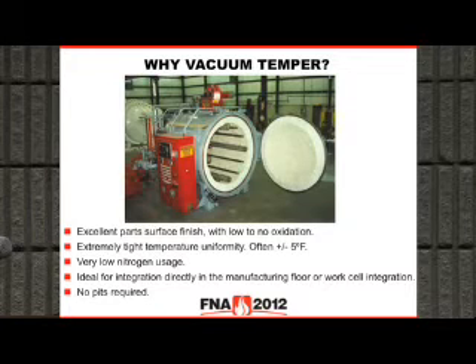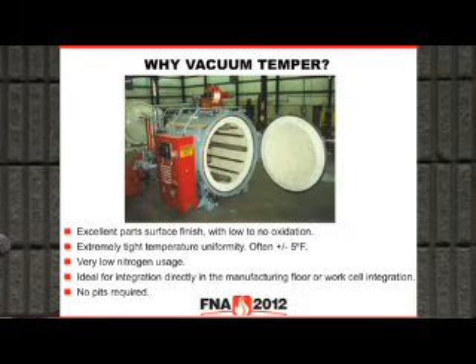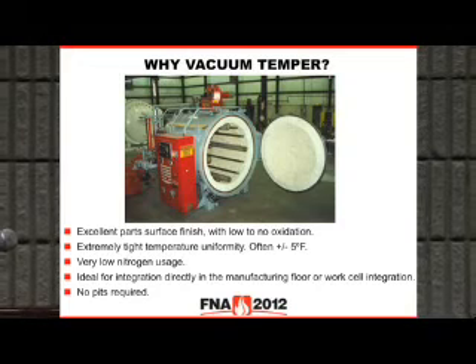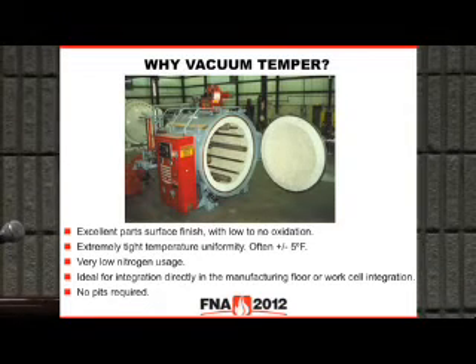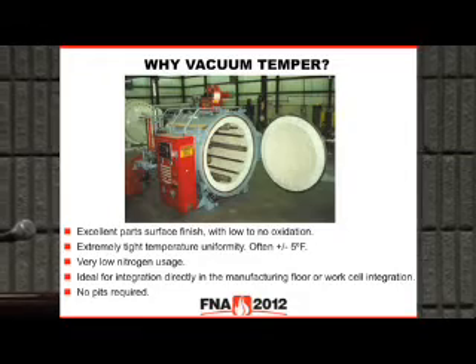Nitrogen usage is low in that we remove all the air from the furnace, and now we just backfill it with one charge. So instead of running 300 cubic feet per hour for 4 or 5 hours, we're going to run just 300 or 350 cubic feet one time in a 36x48x36. So nitrogen usage is low. We actually had one customer who was able to justify buying the vacuum with a 1-year payback on what he would have spent on nitrogen. This was a much larger furnace. We've got some photos of that application.